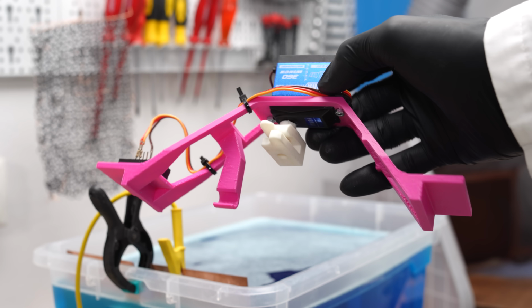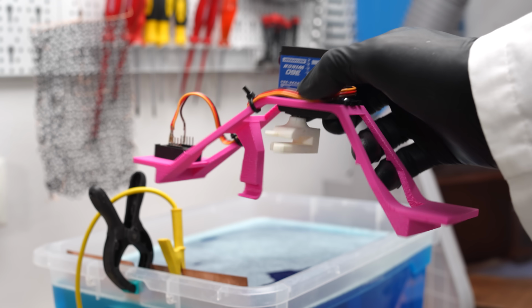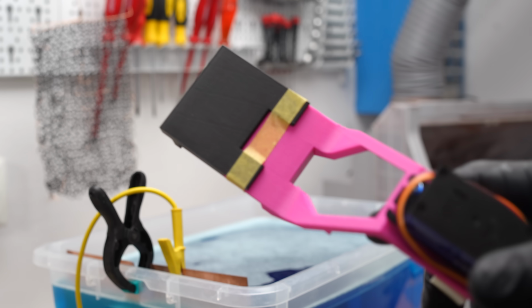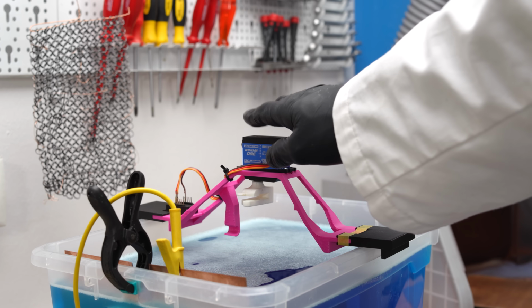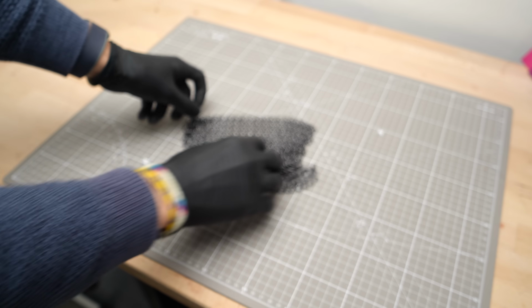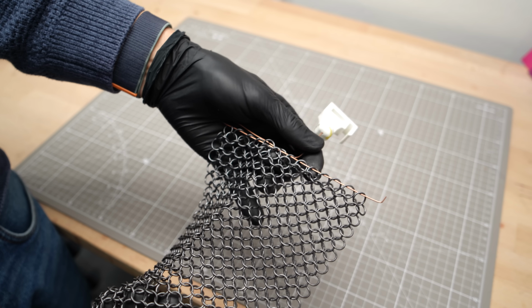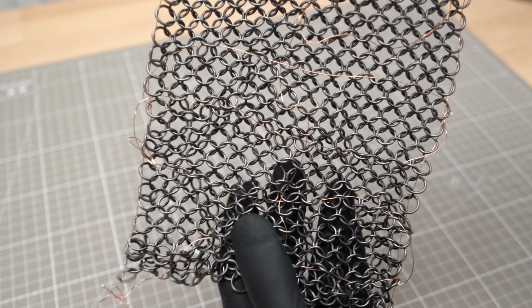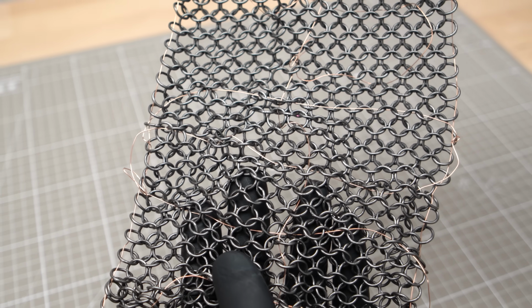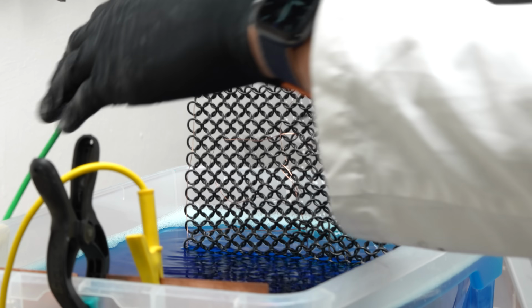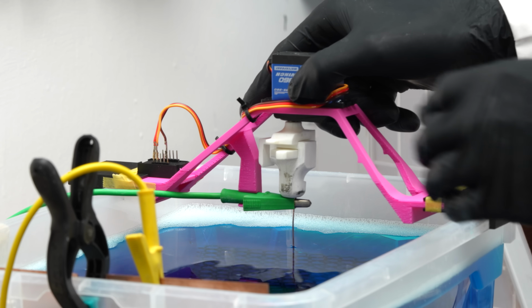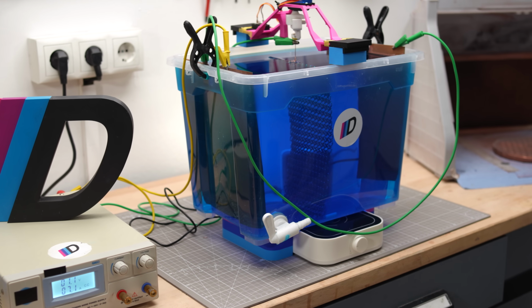Now I'm using my rotary jig to hold the print. It was a bit too short for this tank, so I printed some adapters. Works just fine now. Since the print is flexible, I need to secure it somehow and also run a few wires through it to make sure the plating is nice and even. I'm using copper wires for that. So I bundle everything up, hook it up to the negative pole, and into the bath it goes. Power on and go.